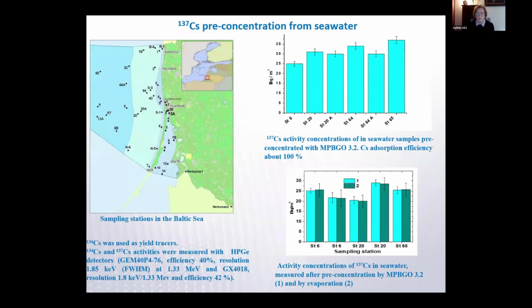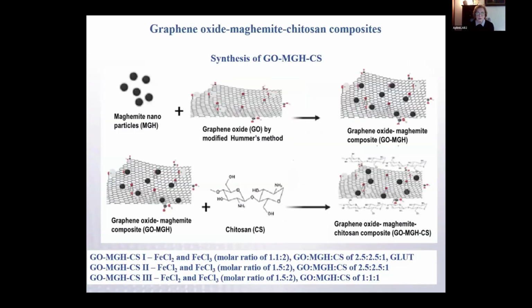Our samples with very good adsorption capacity were used to pre-concentrate cesium from seawater collected at the Baltic Sea, and we have received very good results, and compared our data with the standard evaporation method, and you also can see quite good agreement between these two methods.